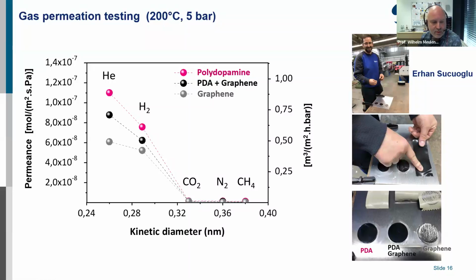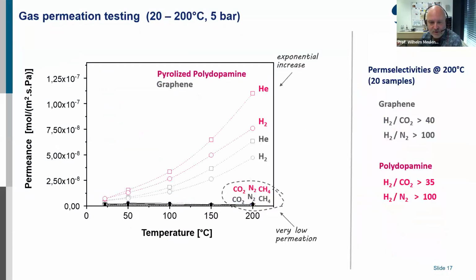So the next step is now to test it in mixed gases and also in humid conditions. And also we want to know how the microstructure of this membrane looks like, because we are sure that it is not a similar microstructure like a graphene layer. We ask now for some TEM measurements, and we are waiting for this, and hopefully in a few weeks we can show you then also the microstructure. And then we also want to prepare a new paper about all these results, which are currently not published.